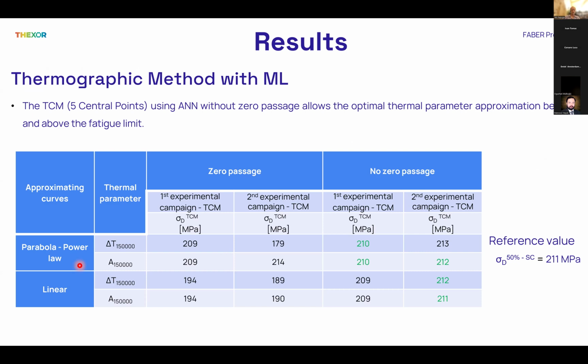We again reduced uncertainty. The staircase reference was 211 with a standard deviation of plus or minus 5 megapascal, and this whole configuration, whether or not considering the zero passage, irrelevant and independent of the linear or parabola power law approximating curve, or independent of the thermal increment or thermal area, all of these results could be considered valid and reliable. So ML did a very huge job reducing the uncertainty of the classical TCM method.